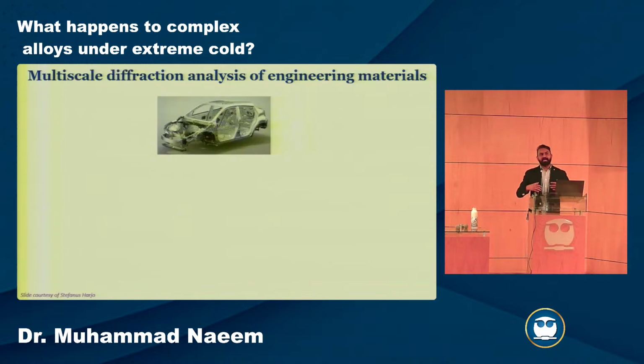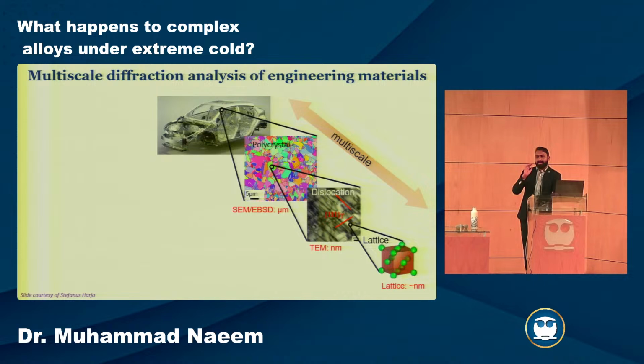So how we do it, as metallurgists, we have plenty of tools at our disposal to undertake this task. So this is one example of, say, an automobile which is made of different materials, composite, titanium, aluminum, a number of them, steel as well. So we can do analysis. We can do analysis at multiple scales. We can use, for example, macroscopic techniques, scanning electron microscopy, EBSD at micron scale, to look at grain structure, look at features at that level. And then we can go further down to nanometer scale with transmission electron microscopy, basically to look at dislocations, which Sandy was talking about, because ultimately they are the ones which dictate these properties.